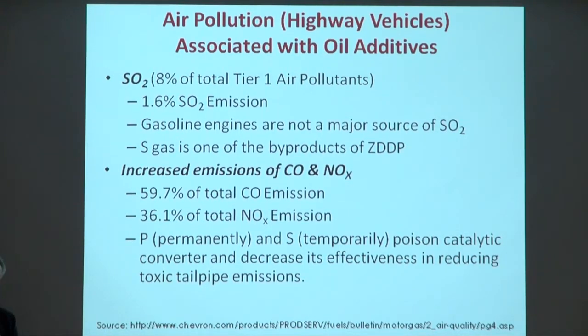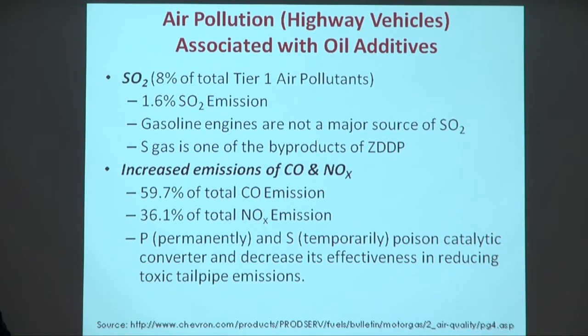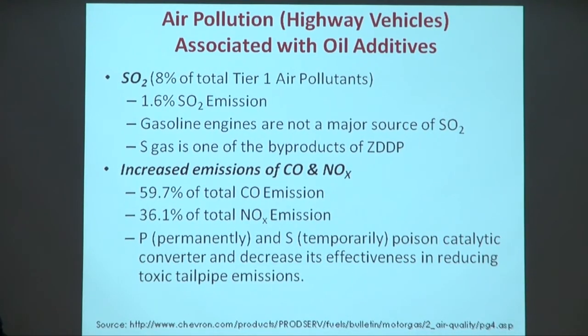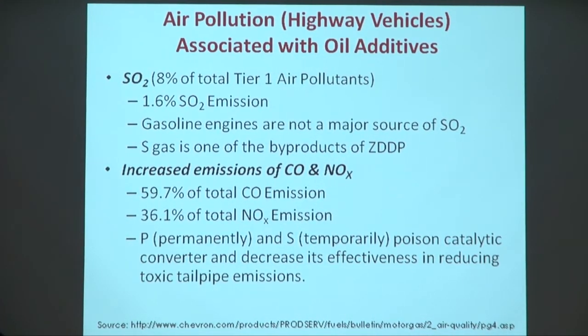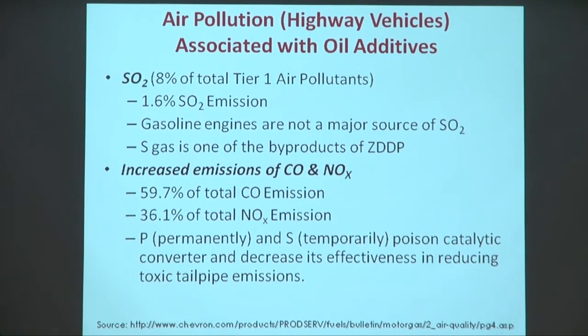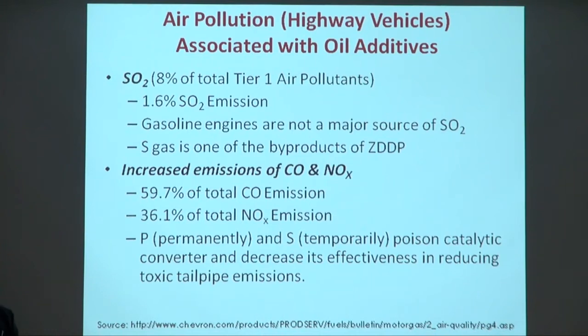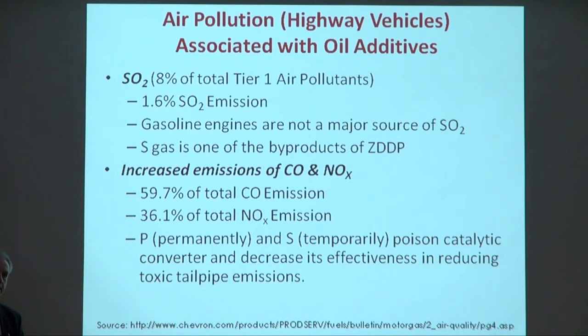So they tend to gradually poison the catalytic converter, causing emissions of CO and NOx to be released more readily to the atmosphere. As a matter of fact, this upsets the optimum operation of the car, because there are sensors in the car that sense that something is going wrong, the emissions are exceeding a certain level, and the consumption of fuel is affected by this optimum now shifting away from the real optimum that the car has been designed for. The result is that during the poisoning of the catalytic converter, not only do we begin to create more emissions, but also the efficiency of the car decreases and the consumption of fuel increases.